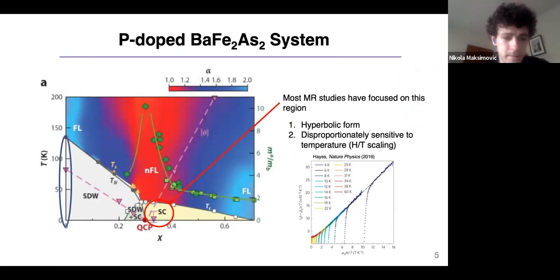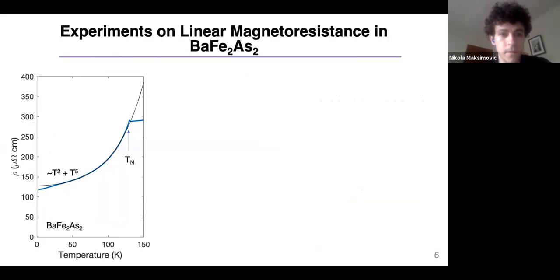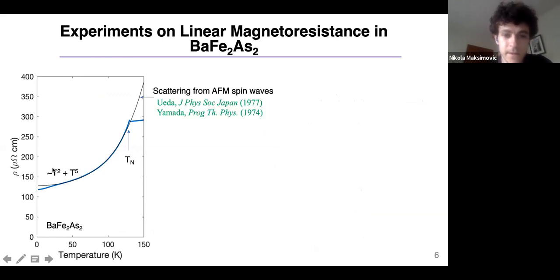In my talk, I'm going to first focus on the spin density wave state, and then slowly move over to the quantum critical regime, and we can see how things evolve from the spin density wave state. So first, I'll describe our experiments on linear magnetoresistance in undoped barium-122. This is an antiferromagnetic metal. The resistance versus temperature follows fairly well a T squared plus T to the fifth dependence. This is something that you expect for scattering from antiferromagnetic spin waves.